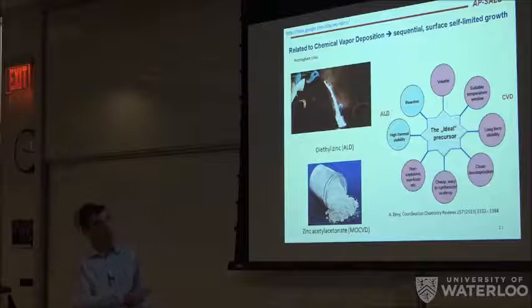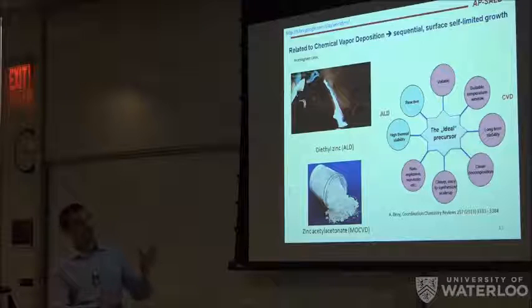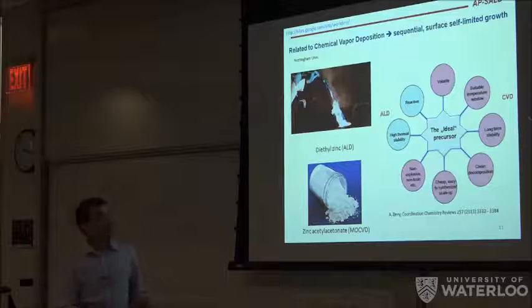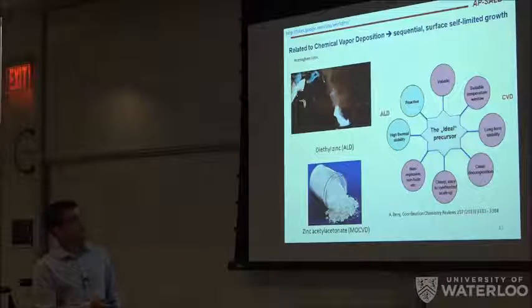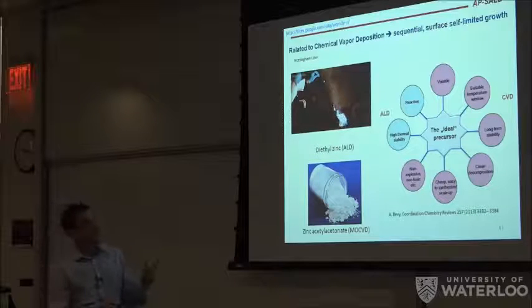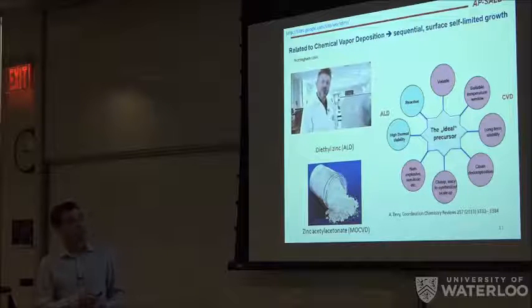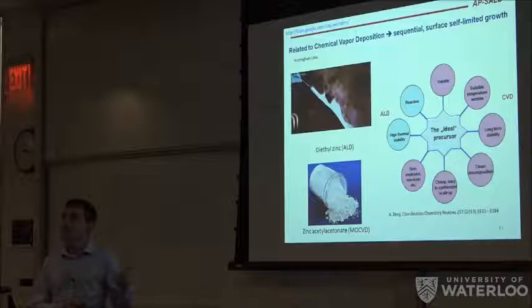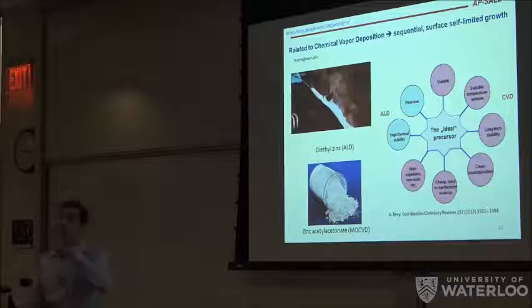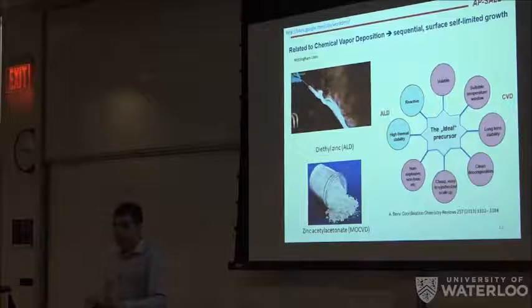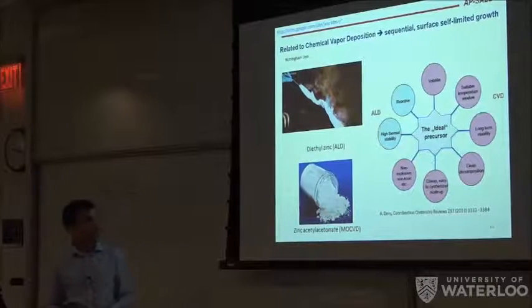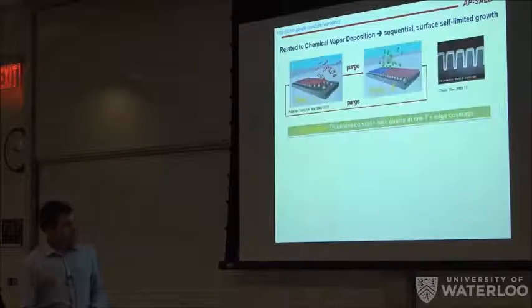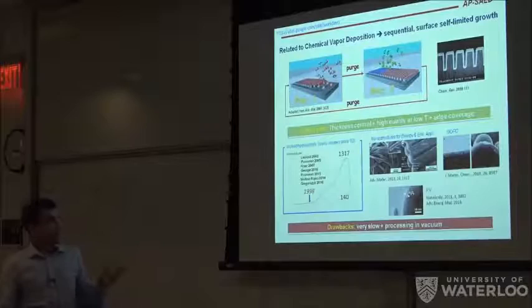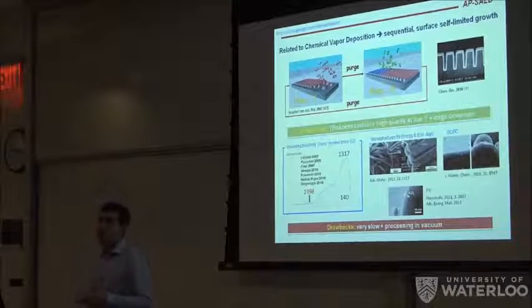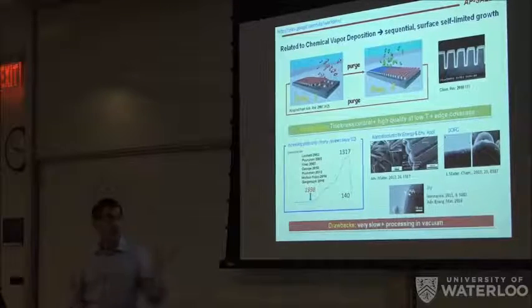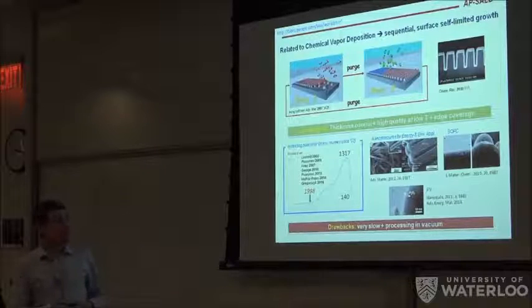And you see here, if you compare the properties required for a good CVD precursor, and you check those for an ALD precursor, they are basically the same, but in addition, for ALD, you need to have a very reactive precursor, but with high thermal stability, because you don't want it to decompose before it reaches the surface and reacts with an active site. So, due to these unique properties, this is a technique that has become very popular. It is now pretty much in every lab, and the labs that don't have it are in the process of buying one or making one.